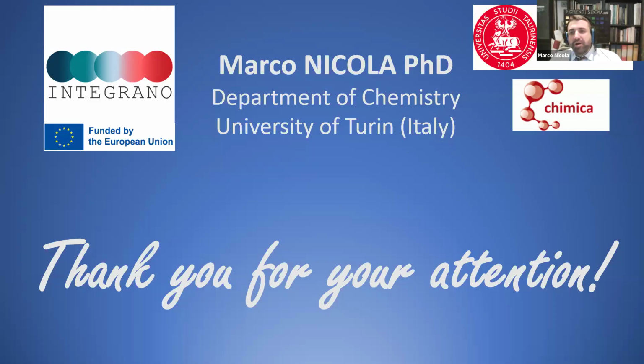So we observe if it is luminescent, basically. There is no other pigment that is luminescent with this, because it's a very rare feature. So if we observe a painting with visible light and record an image in the infrared and there is a luminescence, then it is for sure Egyptian blue, if the painting is ancient, because the only other pigments known that produce luminescence are the cadmium-based pigments that were developed during the 19th century. Okay, so if you are in the ancient world, before the 19th century, if there is something luminescent in the infrared when there is only visible light present, that is Egyptian blue or Chinese blue or Chinese purple. There are no other possibilities.